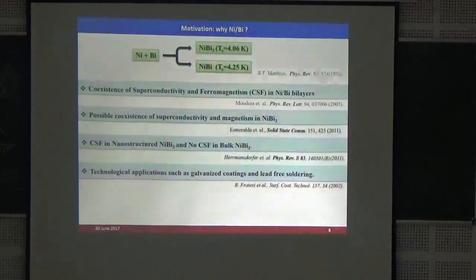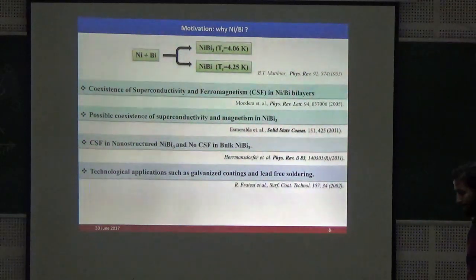So Shiva, you know from your basic textbooks that superconductors are not ferromagnets. Why? Normally, in principle, only 1% of magnetic impurities can destroy complete superconductivity by destroying the Cooper pairs, which is called the pair breaking effect. We don't need impurity in a single phase material, which is a pure superconductor. Now let's find out what the magnetic property is. Some basic things are there which tell you that it cannot be a ferromagnet. What is that? Why do superconductor and ferromagnet not like each other? Actually, the exchange field from the magnetic field normally destroys these Cooper pairs.